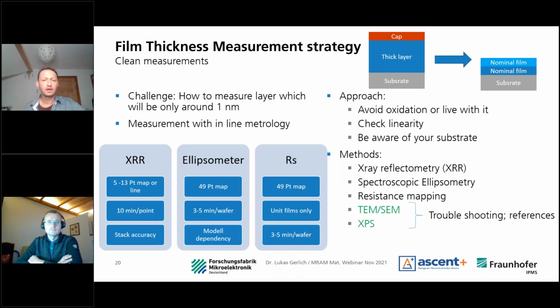So how do we measure a layer from less than 1 nanometer to a few nanometers? Conventionally, we have standalone metrology tools. We avoid oxidization by having a cap layer or an inert material, or we live with it by calculating it. And then we extrapolate this for nominal film thicknesses. So we have to check the linearity, but the linearity for several deposition times is guaranteed, and we have to be aware of our substrates for sure.